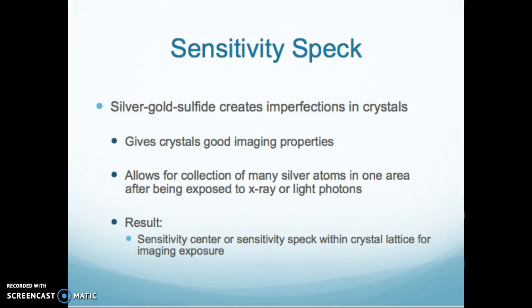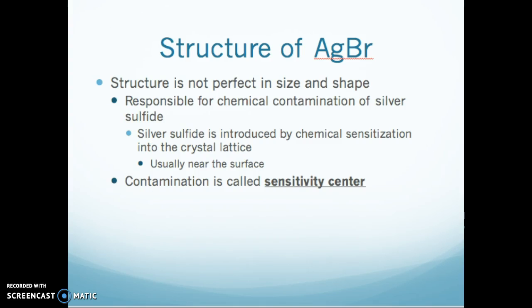Each one of those little areas that we showed, the silver bromide lattice, has a sensitivity speck. The silver gold sulfide creates imperfections within the crystals. That gives good imaging properties, and it allows for collections of many silver atoms in one area after being exposed to light or X-ray photons. The result is a sensitivity center or sensitivity speck within the crystal lattice for imaging exposure. That's where we get the blackness on the film.